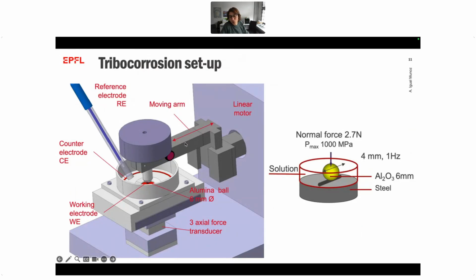Basically, we have a linear motor that moves back and forth and transmits a weight that transmits the load into the sample. We measure the normal load and the frictional load through a 3-axial force transducer, and all inside an electrochemical setup with a reference electrode that allows to impose this surface condition, the potential, and a counter electrode that allows for the measuring of the current, which is directly proportional to the reaction rate. And then we impose these conditions, and we wear, as I said, through this moving arm up and down.